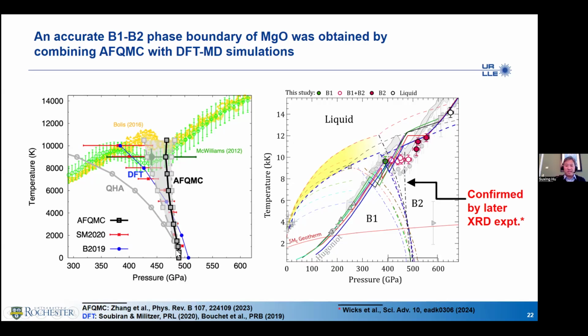One good thing about this is now you can see, if you align the previous experiments together, this seems to suggest this temperature value here is really aligned with the phase transition boundary. Interestingly enough, a very recent experiment with XRD seems to really confirm that the phase transition boundary at this 10,000 Kelvin regime is truly the B1, B2 phase.